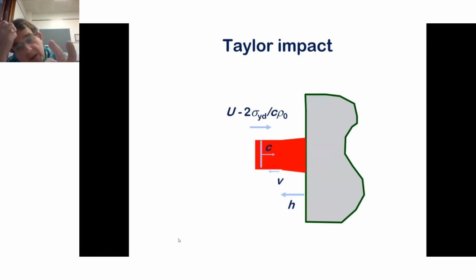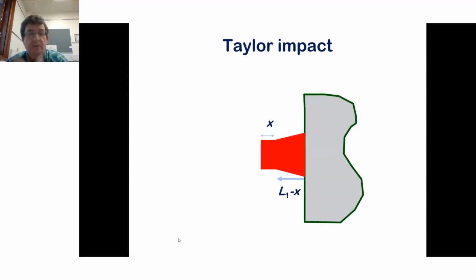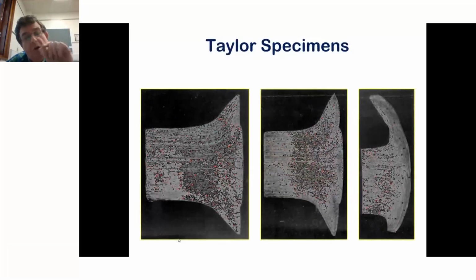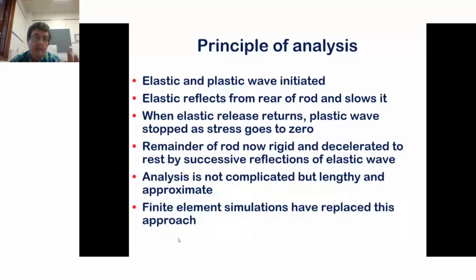So that wave goes back, it meets the plastic wave. What does it do with the plastic wave? It interacts with it, it takes away stress, it slows that plastic wave down and eventually stops it. You're left with one part of the rod at a certain deformation, another part of the rod at a very strong deformation. And here we have 3 examples of Taylor impact specimens obtained at different velocities. Now, the shape is different because the strain rate was different. Yield strength depends upon strain rate. So I hope that you can see that we're talking about elastic waves, plastic waves.